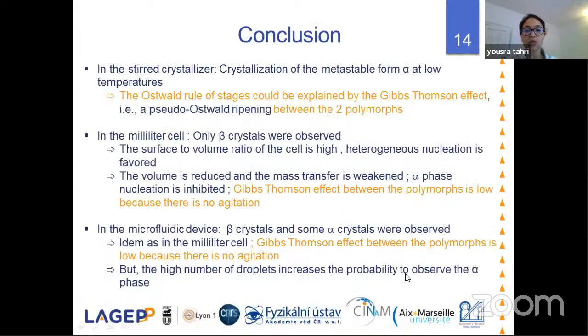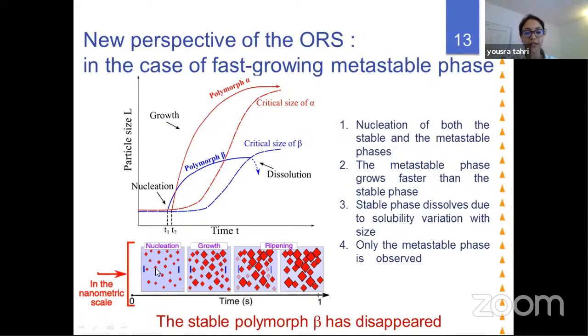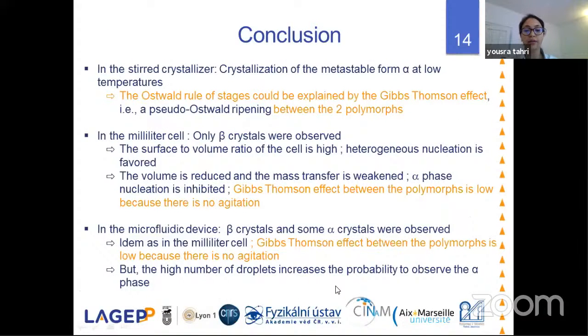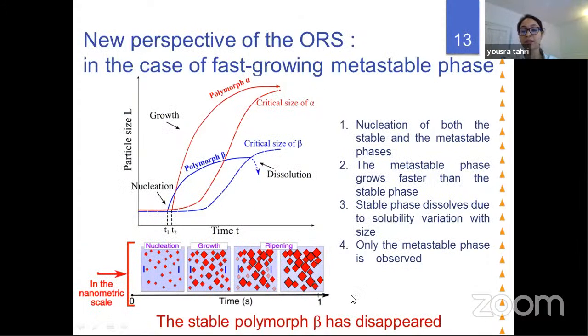So this permits us to have a new perspective on the Ostwald rule of stages in the case of a fast growing metastable phase: on the nanometric scale, both polymorphs crystallize at the same time, but because the metastable phase grows much faster than the stable one, the stable phase at some point will find itself undersaturated and will dissolve, and what we will observe at the macroscopic scale is only the metastable phase.